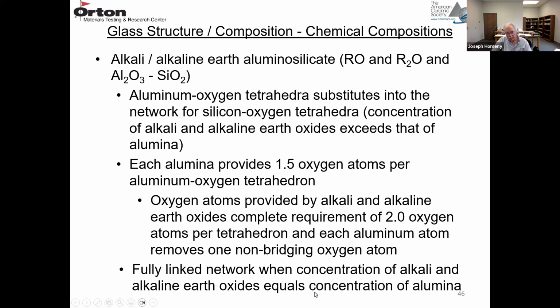So what's happening, the alumina additions actually make a fully linked network. So as you're adding aluminum ions, you're creating more cross-linking. And finally, when the alkali and the alkaline earth oxides are the same concentration, you have a fully linked network again.